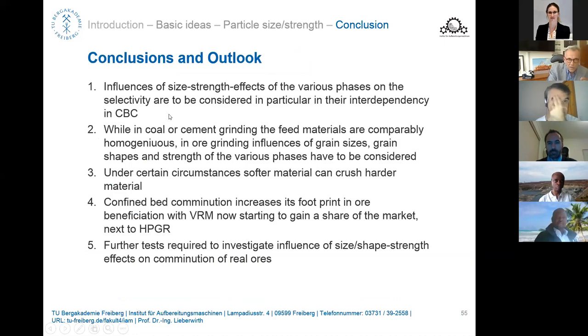So, conclusion: influences of size and strength effects of various phases on the selectivity ought to be considered, in particular in their interdependency in confined bed comminution. While in coal or cement grinding the feed materials are comparably homogeneous, in ore grinding, influences of grain sizes, grain shapes, and strengths in the various phases have to be considered. Under certain circumstances, the softer materials can crush the harder material, and confined bed comminution might increase the footprint in ore, and that's why we have to investigate this.